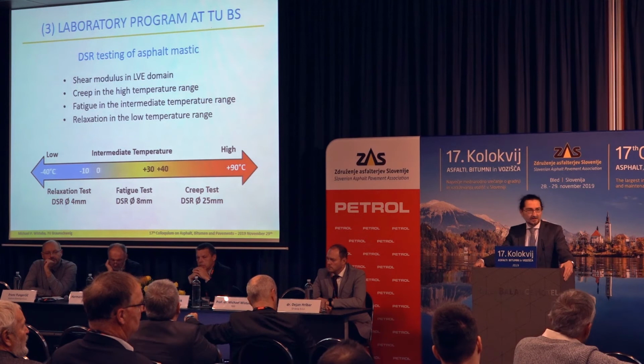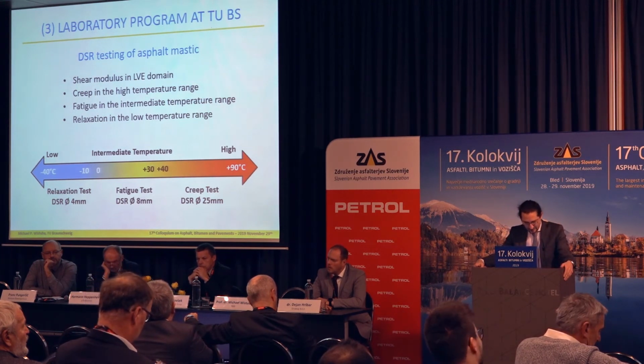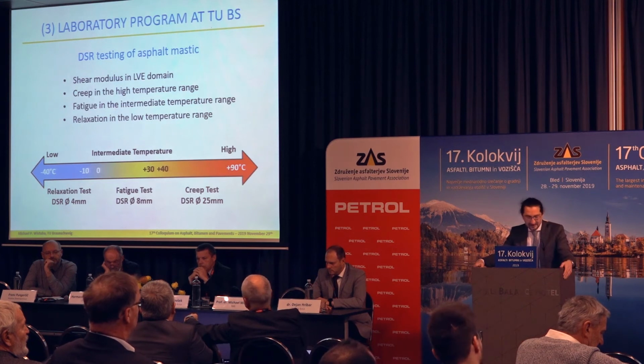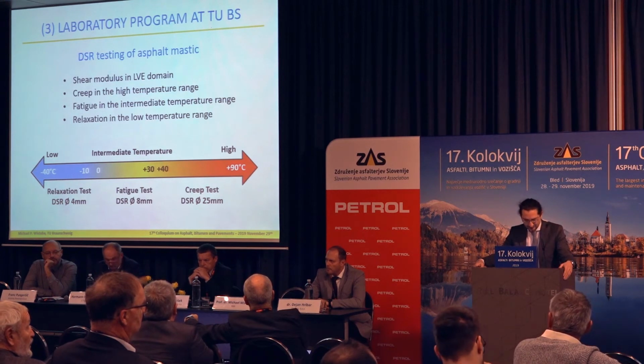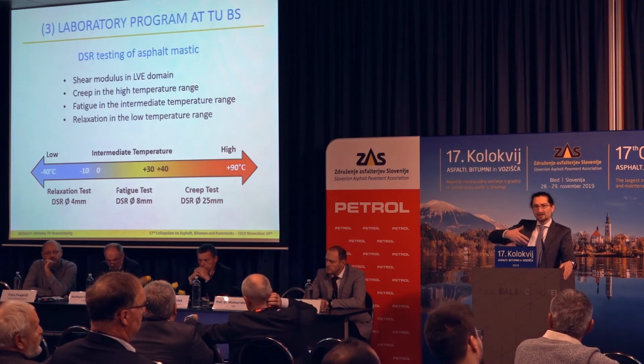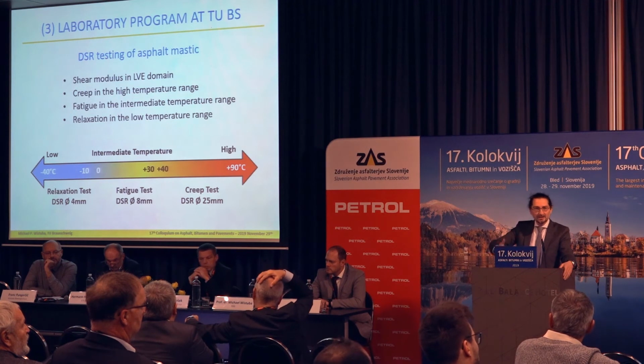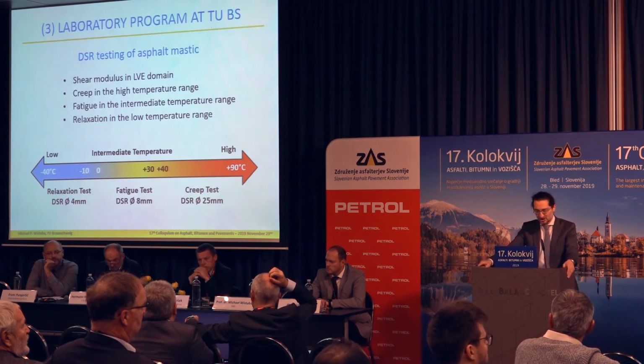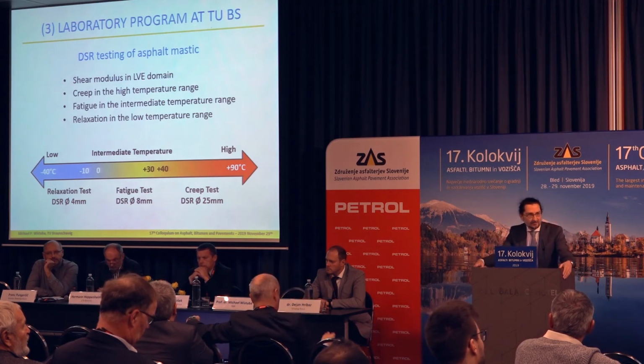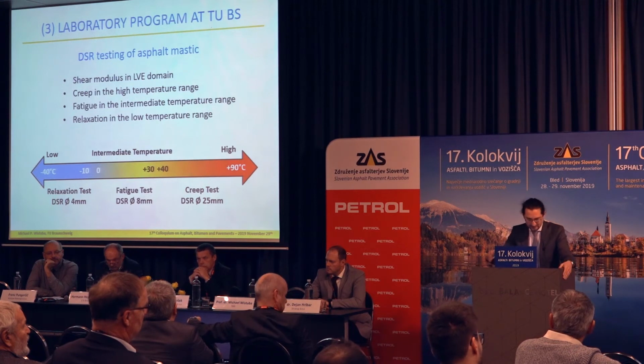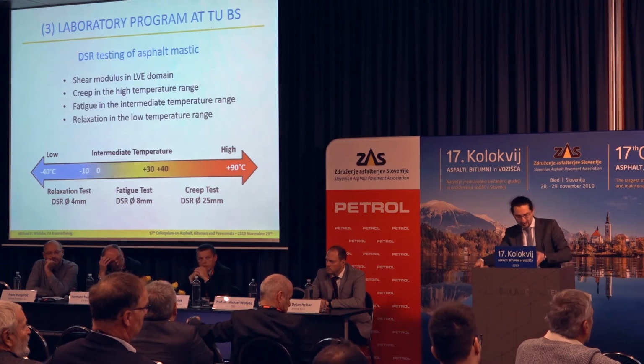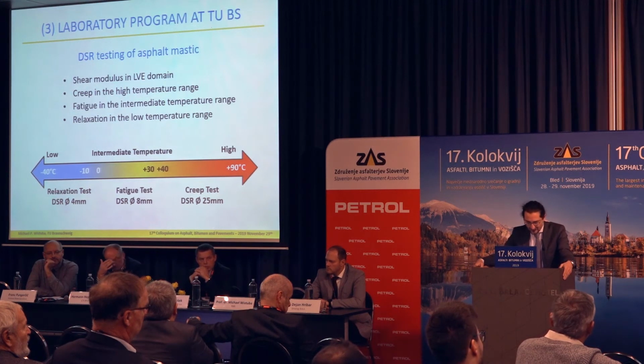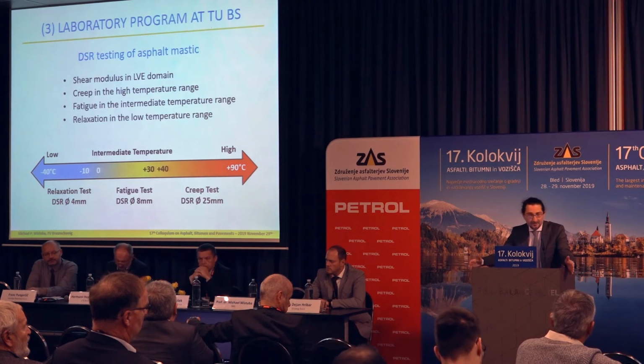So what did we do as a laboratory program at TU Braunschweig? We studied asphalt mastic properties with the DSR in the linear viscoelastic domain, which means stiffness properties, here considered as the shear modulus, but also behavior in failure modes already, which means fatigue and low temperature cracking and permanent deformation. So we tried to cover the full temperature range in service, which means temperatures from -30 to +90 degrees Celsius. And we developed DSR tests for the individual temperature range for all these three temperature ranges.